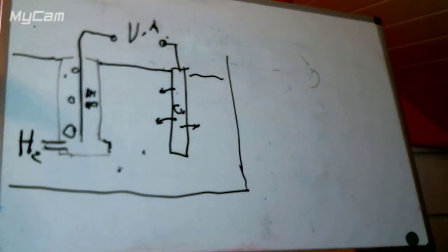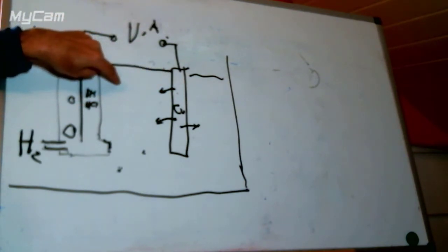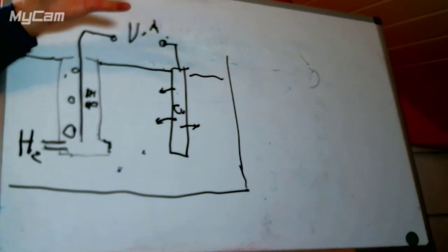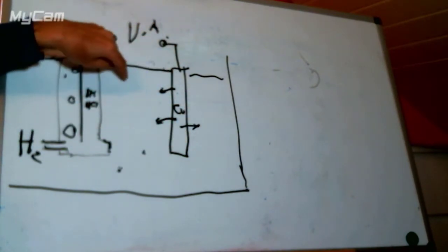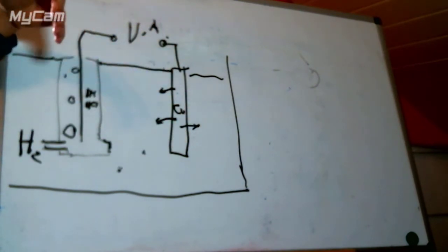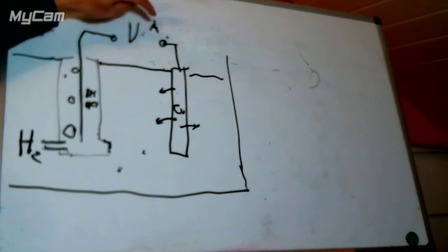If we think about it locally, when the copper leaves, it's still here hanging around close to the electrode, so the local concentration of copper close to the electrode is higher than the concentration over here far away from the electrode. And it can't just jump over here magically, it has to diffuse over time. Unless we're stirring it, it has to diffuse away. And so we have a kinetic process,